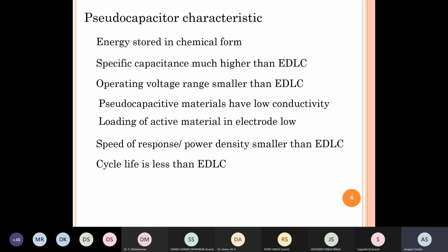Okay, so therefore the speed, which essentially means the power density, of a pseudocapacitive electrode is also smaller than EDLC. And also the cycle life of EDLC is much higher than a pseudocapacitor, and that again has to do with the fact that in a pseudocapacitor there are greater changes which happen to the electrode structure compared to EDLC, where there is essentially no change in the solid electrode part of the EDLC.